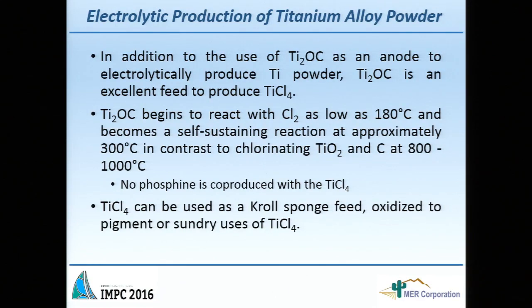And we had a joint venture with them to work out how to eliminate chlorinated hydrocarbon. And the only way to do it at that time was to go above 800 degrees. And at this temperature, corrosion becomes a real problem. So low temperature chlorination is always favorable, but you have to eliminate the chlorinated hydrocarbon. The carbon in the Ti2OC is not free carbon, it has already gone to very high temperature, so you do not form chlorinated hydrocarbon. And you can produce TiCl4 at low temperature.